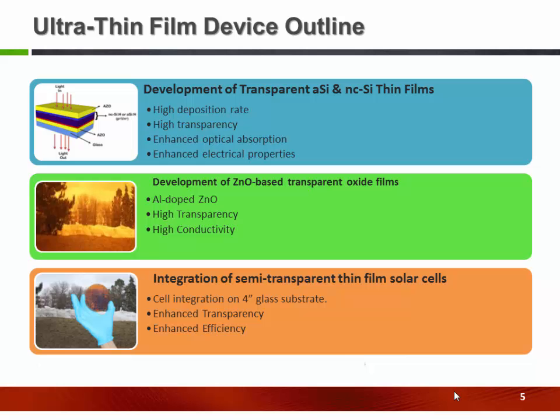For the device structure, we use the normal PIN structure, but we made a little innovation by using aluminum doped zinc oxide as a TCO for the back and top contact layer. We didn't use a metallic contact. We developed a semi-transparent amorphous silicon and nanocrystalline silicon. We developed a very good aluminum doped zinc oxide TCO layer with high conductivity and high transparency, and we integrated it in larger scale devices.